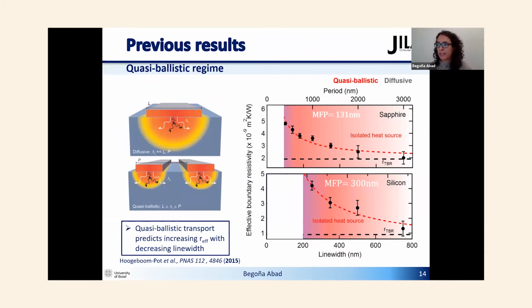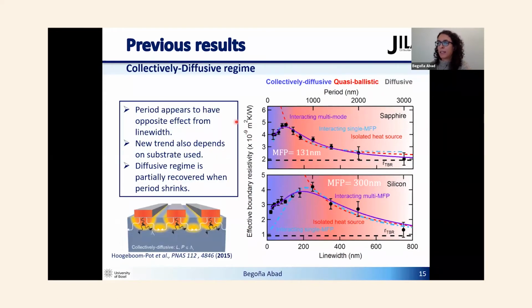We did this analysis for different nanogratings with different line widths. And we could see that as we were reducing the line width more and more, this parameter that I was talking about, the effective thermal boundary resistivity, increases and increases. And this is a sign of quasi-ballistic transport, which predicts that the thermal boundary resistivity goes up. Not only that, but if we study also as a function of period, we see that there is a turnaround in the behavior towards diffusive predictions when the period starts to be also comparable with the phonon mean free path. We did that for two different substrates, sapphire and silicon, and we saw the turnaround happening at the lengths that match the phonon mean free path of these two systems.